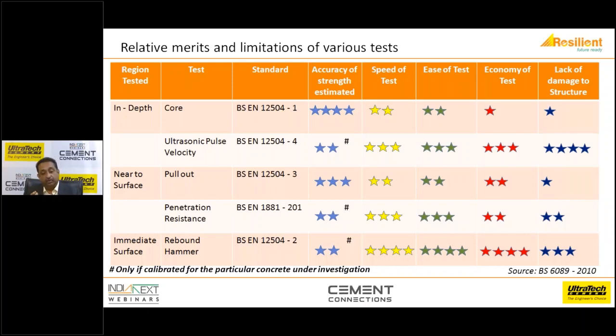And the more the stars, the better the impact is. So if I look at the accuracy of strength estimated is what you need to find out, then core is what you need to actually look for, not the Schmidt hammer. But if you are looking for a quick and easy test to estimate whether it needs to be further investigated, then a rebound hammer may work because it will give you a quick speed of test and the ease of test is better, the economy of the test is better, and it does minimum damage to the structure.